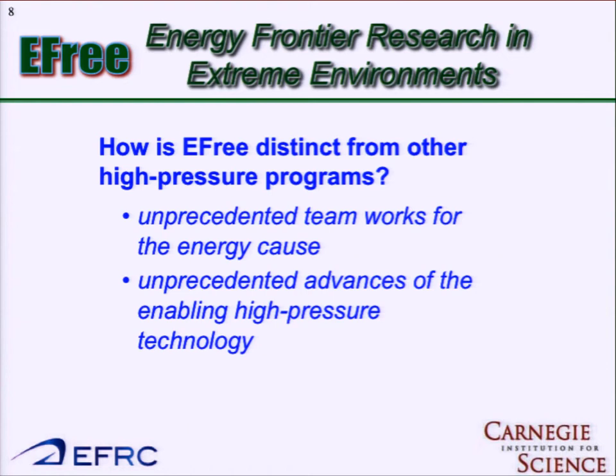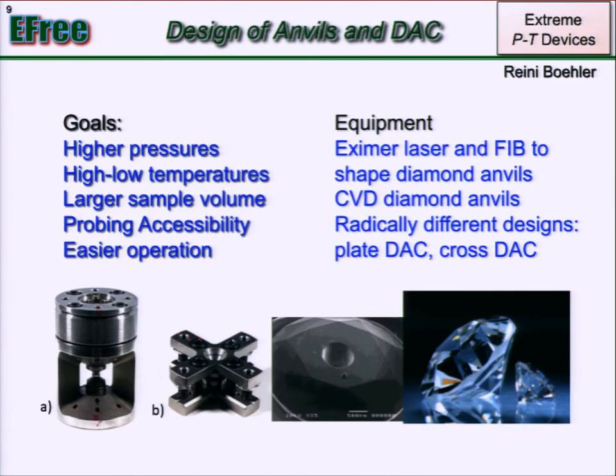And so we're not limited by any of this existing, what we have, because we also have collaboration. Okay, so for the high-pressure technique, we are developing low temperature diamond cell. We develop different kinds of cell with different openings, for neutron and for synchrotron, each one optimized for a different part. We even grow our own diamond because natural diamond is not quite good enough, so we have a CVD method. We can grow our own diamond, make it bigger and purer, and with better impurity properties so it can work better as an anvil.